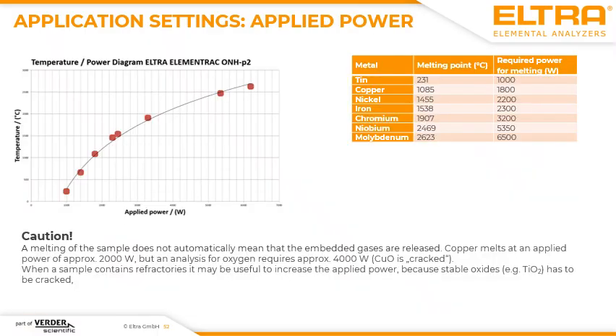In addition, you will find here a temperature curve of the ELEMENTRAC ONH-p2. So there you get a feeling about the applied voltage or power to the analyzer and the resulting temperature. For example, when you apply a power of approximately 1800 watt, you usually get temperatures of about 1000 to 1100 degrees Celsius, and copper will melt. This applied power for melting is a rough estimation of the minimum power you need.